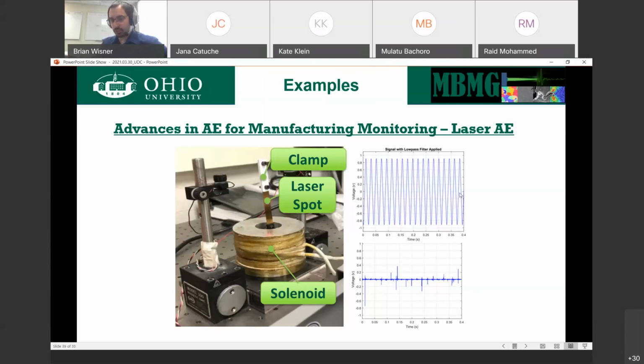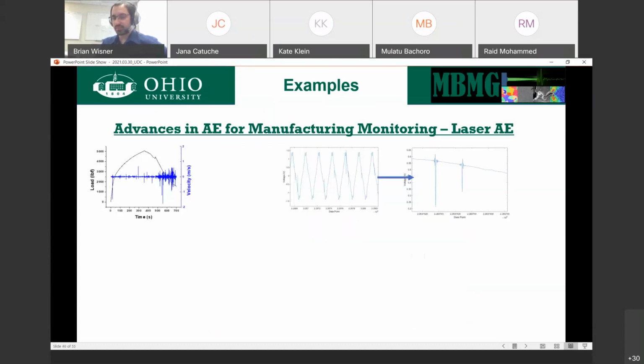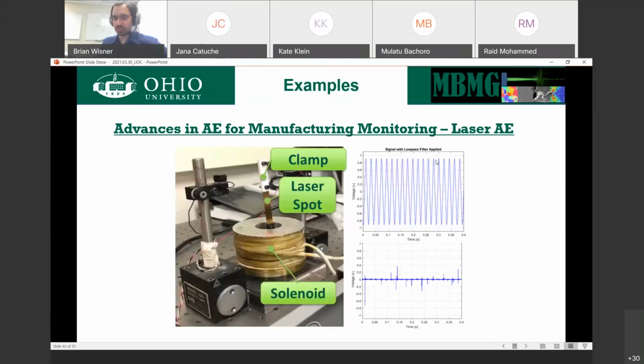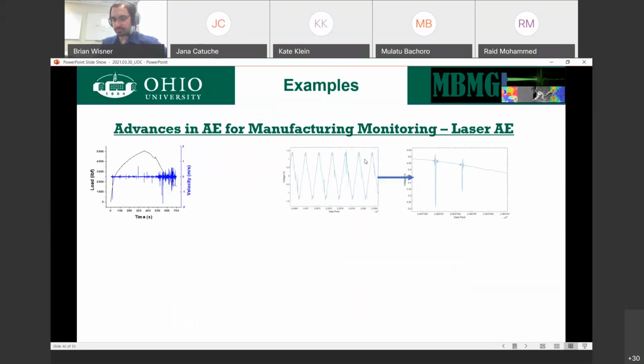What we're seeing here is two approaches to non-destructive evaluation with one sensor. The top monitors the resonant frequency. We're vibrating this at the theoretical resonant frequency of the material. Once a crack grows long enough, the amplitude should drop. The bottom is acoustic emission. All of this comes from the same raw signal, except filtered. So we can see very clearly that embedded within this vibration is this piece of information. We can also see the frequency that I'm applying here. There's an additional little error here with these bumps at the top, just to show you how powerful this can be. That was a fractured grip. We were monitoring nowhere near the grip, yet we knew the grip was fractured.